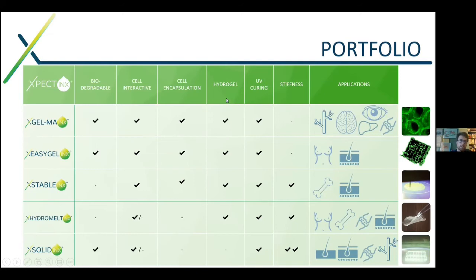Now, one of the downsides of Gelma is it can be 3D printed, but it really needs a sweet spot of parameters to make it a bit processable. So therefore, we also offer our next generation of gelatin-based materials, which have the same properties, but are a lot easier to print. And we already have some proof of concepts with adipose tissue and skin tissue. And then our last one of our ECM mimics is a non-biodegradable synthetic hydrogel. It's called XSTABLE, which is very easy to print. It has a lot of the same features as gelatin, but it's a lot more robust, almost rubber-like, meaning it's suitable for more mechanical, resilient tissue types like bone and skin. And then we have our scaffoldings, which are printed from the melt.